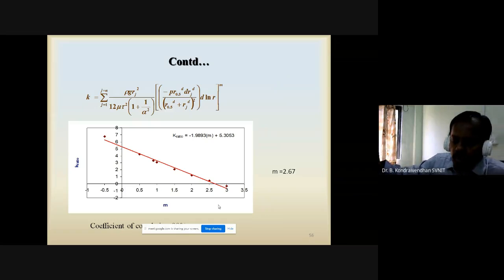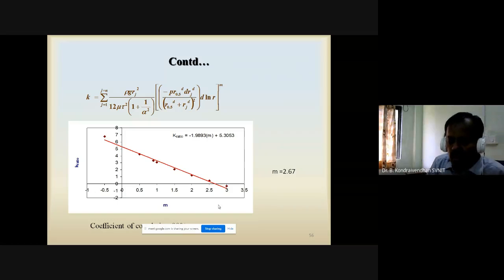That is called the K ratio, and we have taken m values randomly, like 0.5, 1, 1.5, a number of values. Then we have plotted a graph between K ratio versus m, and from the curve we got the actual m value. So we got the interconnectivity factor for the cement paste, m equal to 2.67.